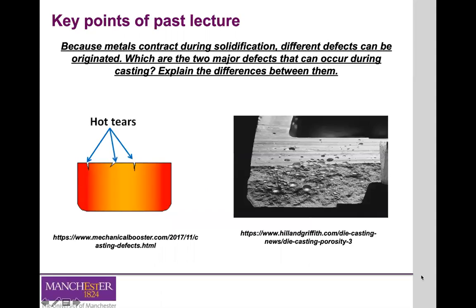Several defects can occur during metal casting. Surface defects don't have as important an impact on the mechanical properties of casted parts as, for example, hot tears or porosity. Hot tears in castings normally occur because the casting is not able to shrink freely during the cooling or solidification process due to constraints in various portions of the molds and the cores. Porosity caused by gases evolved during solidification can also be a significant problem because of its adverse effect on the mechanical properties of the casting. The goal is always to cast a part that is 100% solid.